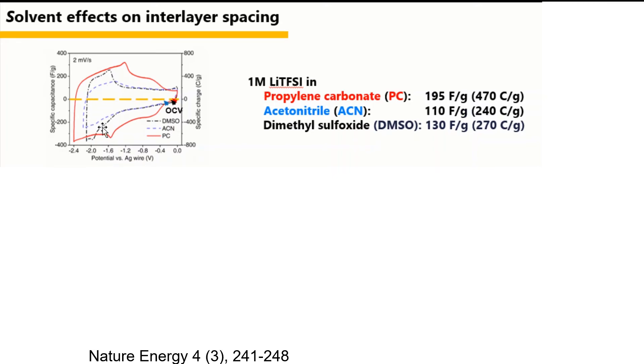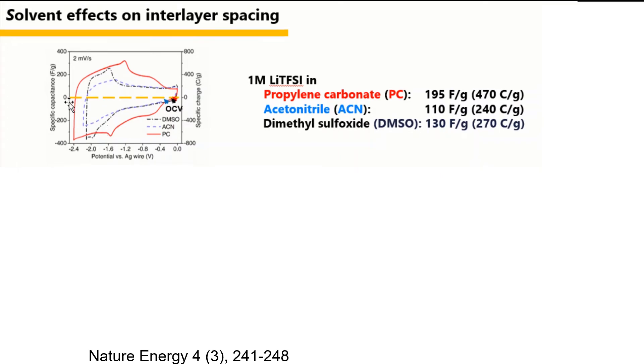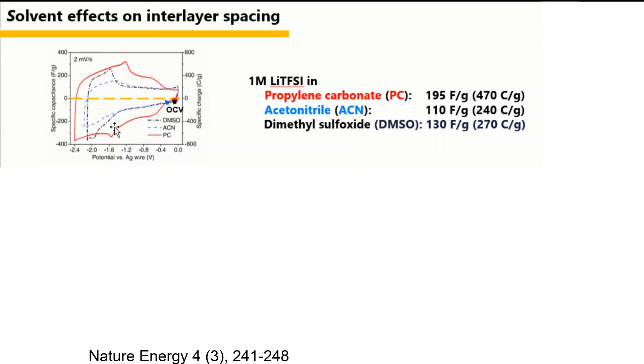Using DMSO as solvent shows clear redox peaks on the CV. Surprisingly, for propylene carbonate (PC), it shows strong redox peaks with almost two times the capacitance compared to the acetonitrile and DMSO systems. It is very interesting to observe that by simply changing the solvent, the electrochemical behavior is totally different.